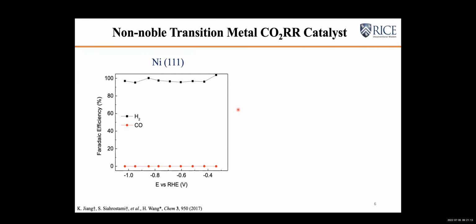At the beginning, we were thinking about whether we could activate some of the earth-abundant transition metals like cobalt, nickel, iron, and so on, because they have been widely investigated as water splitting catalysts. So we were very naively thinking about whether they could also be utilized in CO2 reduction. At that time, very few studies had focused on these transition metals, for two reasons. Number one, they were generally considered very, very good HER catalysts. So you never want to start with a catalyst for CO2 reduction that has excellent competing HER activity, right?